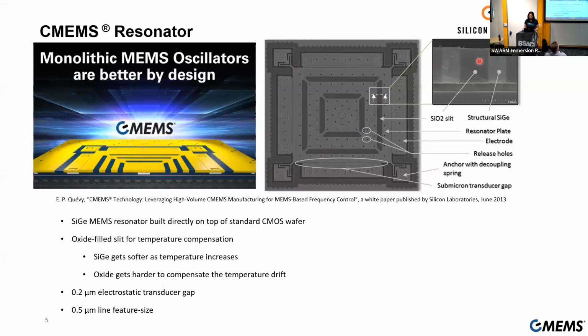So on the right side, there's a zoomed-in cross-section image that is making a cut here. In this image, you can see that we have silicon dioxide being embedded into the silicon germanium structure layer. The purpose of having the oxide slit is for temperature compensation. Silicon germanium will get softer as temperature increases, and that will cause problems when we are doing timing reference.